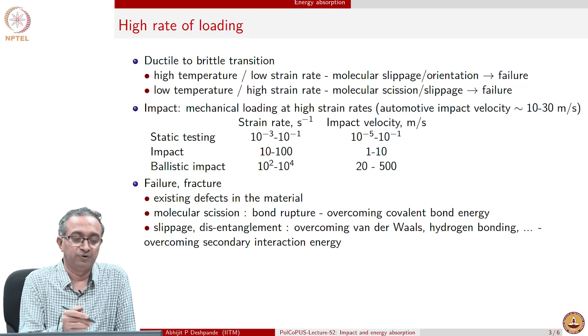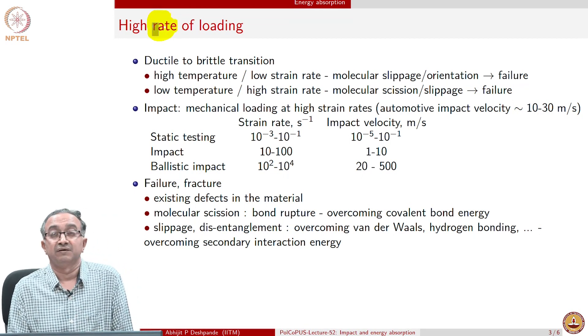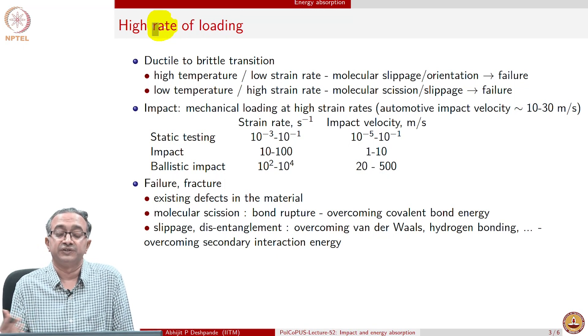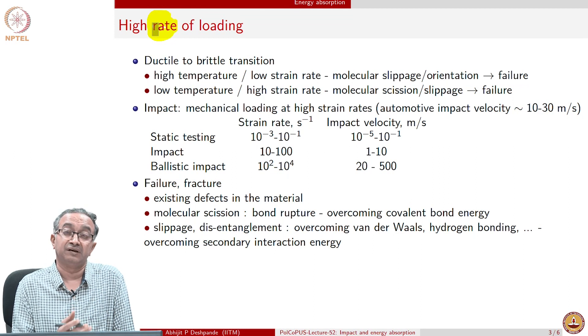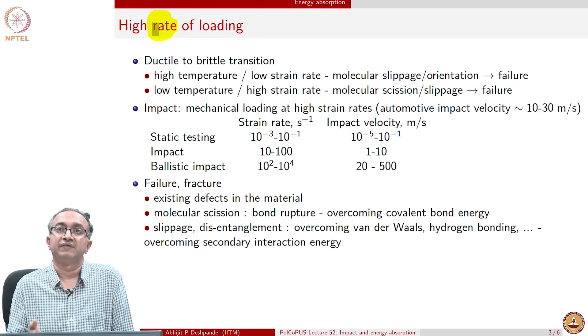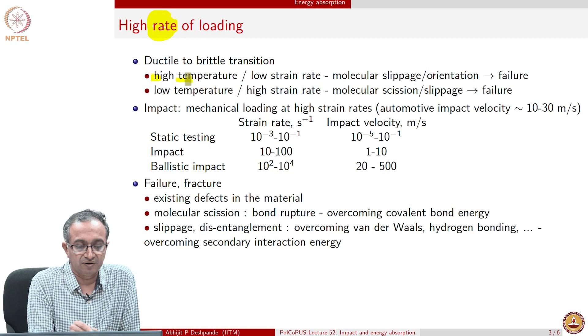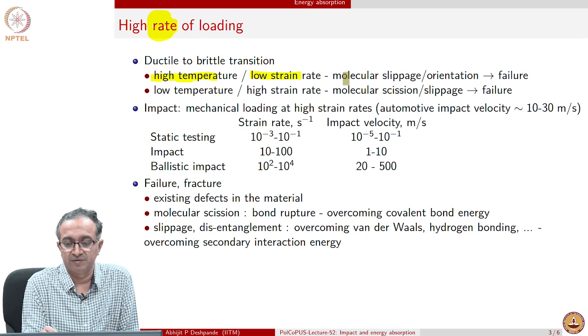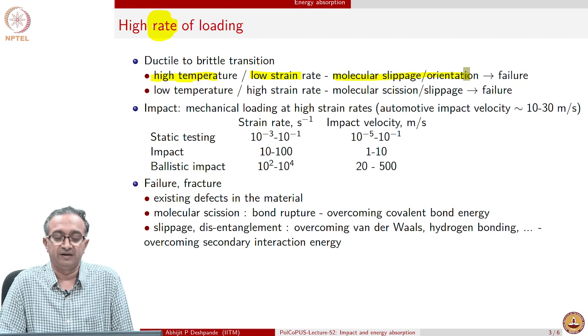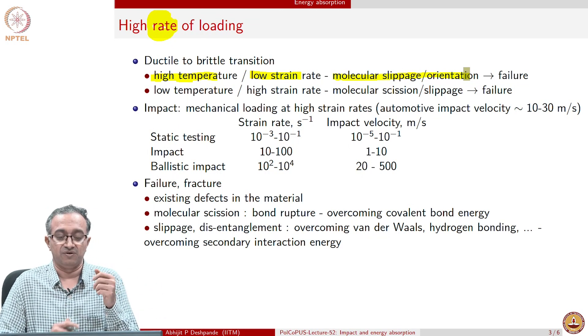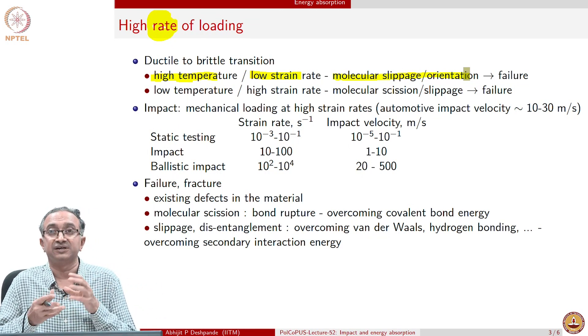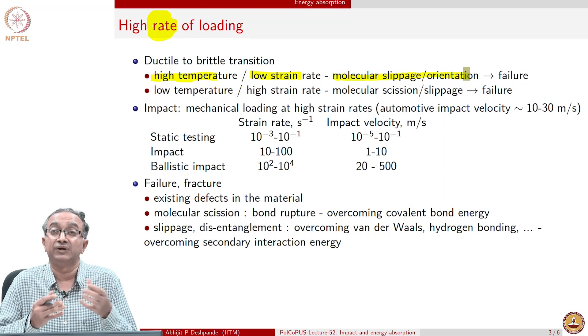Generally, the rate of loading is an important factor — how high is the rate of stress or strain application. This can lead to behavior changing. We have already discussed that at low temperature you might see a very brittle material, but at high temperature you might see a flexible and soft material. If you go to high temperature or low strain rates, mechanisms of molecular slippage and orientation start happening and eventually failure occurs.